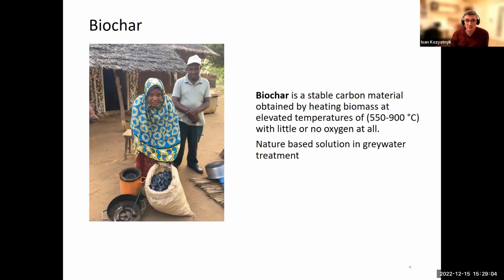However, biochar, in comparison, for example, with activated carbon, has a limited ability to selectively adsorb pollutants at high concentration due to the low porosity of biochars. One way to improve the performance of biochar in environmental remediation is various modification methods, including activation, surface oxidation, impregnation of metal oxides, and functionalization.